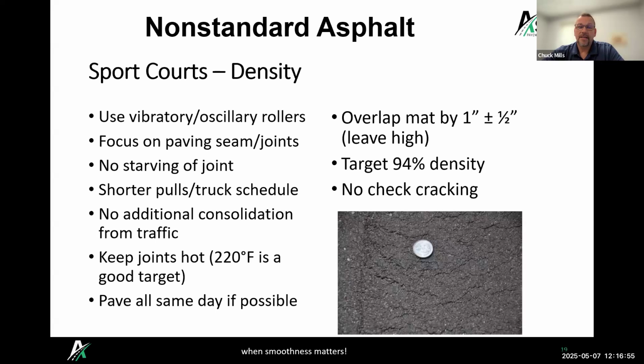Then when we are paving the pulls, we want to make sure that we're overlapping the mat. And again, that's just best practices on making sure that we're getting density at those joints. Typically, we're going to target a little higher density on a court application. 94% is a good rule of thumb, because again, we're not getting that extra consolidation from traffic. And then we want to make sure when we are rolling it that we're not getting any check cracking from over rolling or rolling when the mat gets too cool and things like that, because that can create a lot of tiny little cracks that can let moisture into the surface.